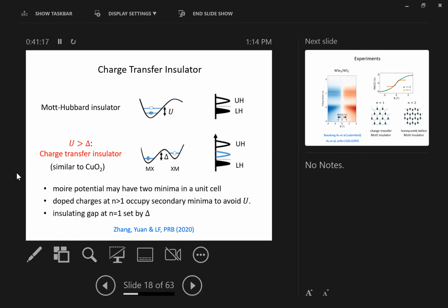Okay, and in this case, the physics is kind of interesting. When you start with the Mott insulator state, every primary potential minimum is occupied. Add one more electron. Instead of a double occupancy, the added electron wants to occupy the second potential minimum. They want to transfer into a different site in the unit cell, a different sublattice in the unit cell. Yes. So U is like 100 meV? U is more like 100 meV. Yes, that's our estimate.